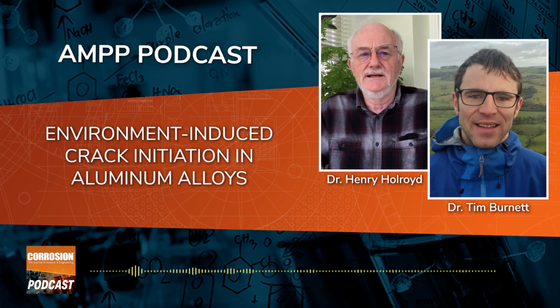I think in the first review article, looking back over the development of aluminium alloys, we were able to show that if you have a 7000 series alloy, with the additions of zinc and magnesium, you add the zinc and the magnesium to have a higher strength material because you need more of the precipitates to form. But you reach a limit essentially to how much zinc and magnesium you can add to the alloy before you really just run straight into this issue of environmentally assisted cracking. And it's interesting that you can add different alloying additions to actually get a little bit further. So then keep a higher zinc and magnesium content and still have good performance from your material. But we've maybe reached the limit, and it's a bit of a shame really that the highest strength materials that we can make are some of the very most susceptible to this